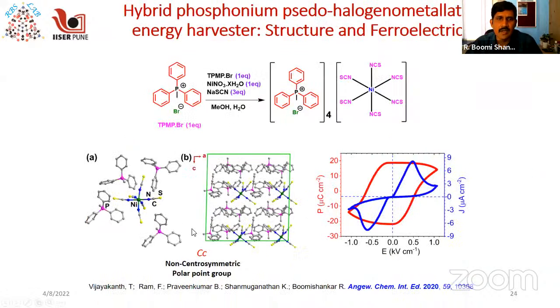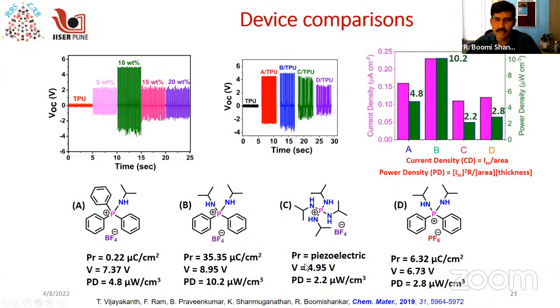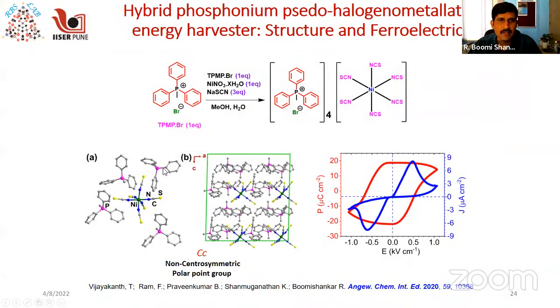However, what you see is that the voltages that are generated are very low because the molecule is organic in nature. So in order to increase the performance, we changed from an organic salt to an organic-inorganic hybrid salt, and we used a simple phosphonium salt which has phenyl and methyl substituents, which helps in reducing the symmetry of the system. And the inorganic component, or the anionic component, comes from the nickel isothiocyanate coordination complex.